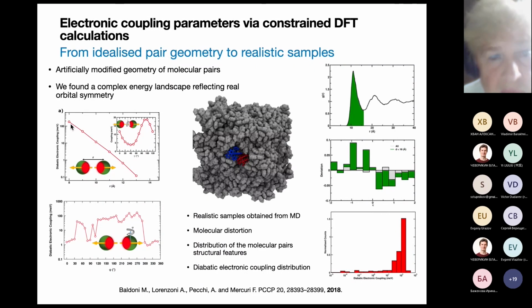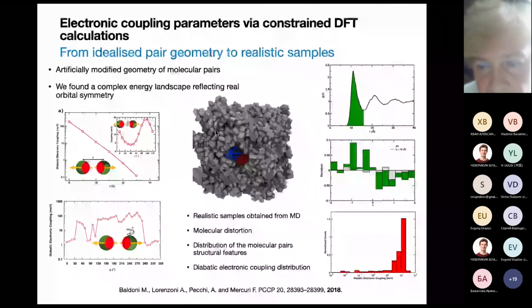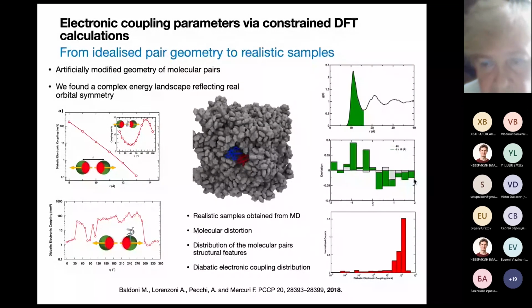Here you can see how this quantity is related to the distance between the two molecules, and really it's influenced by the rotation along some specific axis. From this idealized structure, we go then to a more realistic sample of molecular aggregates. This is what you can get out of a molecular dynamics simulation. We extract all the molecular pairs in several of these samples, do an analysis of their morphological and geometric configuration, and calculate the electronic parameters for each couple, and then provide a distribution of these diabatic electronic coupling parameters.